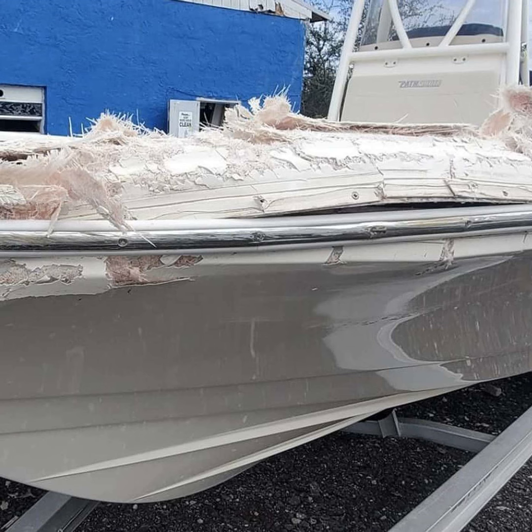I mean, you can build some glass up and fair around the edges and kind of shimmy here and there, and you can bring it up past grade and hide a repair in certain areas. But using a hull side, for example, if you were to build your glass up too thick and then just try to make a ramp around it with fairing compound or Bondo and try to kind of smooth it all together, then when you look down the side of that boat, you're going to see a hump in it, right? And plus gel coat, so you're adding another little bit that's going to actually reflect the light. Yes, exactly. So it's noticeable. You have to bring it back to that same surface profile that you started with.